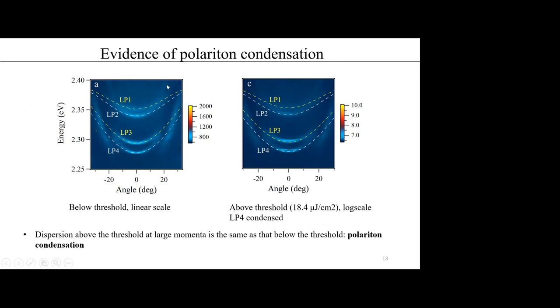To make sure polaritons condense in the strong coupling regime, firstly, we replot the dispersion above threshold in log scale, and we compare the dispersion with the below threshold. Here we can see that the dispersion at large momentum above threshold is the same as that below threshold. This indicates that we do observe the polariton condensation in the strong coupling regime. Under higher power, polaritons can condense at LP3 and LP4 at the same time. Further increasing the pumping power can destroy the perovskite microplate. We hope two thresholds can be observed if the quality of the perovskite microplate is improved further.